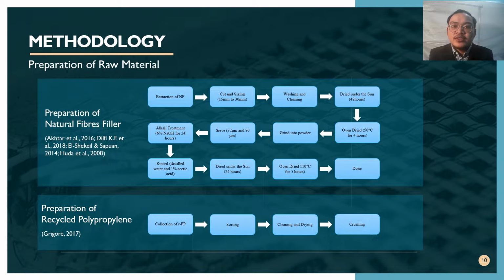Preparation of raw material. For the preparation of natural fiber, the steps are taken from a previous study, where the process is as follows. Kenaf and oil palm empty fruit bunch are extracted to obtain the fiber, known as KF and OPEFB. The fiber will be cut to a dimension of 15 mm to 30 mm. Then washed and cleaned to eliminate any contaminant that may affect the result. Next, the fiber is left to dry under the sun for 48 hours, then put in the oven for 4 hours at a temperature of 50 degrees Celsius until the moisture is gone.